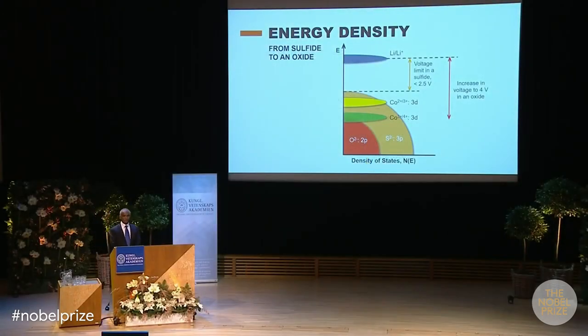There were two major issues with the sulfide cathodes. First, we cannot get more than 2 or 2.5 volt. Second, the sulfide cathodes did not contain lithium ions in them. Therefore, one has to use lithium metal anode that posed safety concerns, fire hazards. In fact, there were attempts to put lithium batteries containing lithium metal as the anode into the market, but then they were abandoned in the 1980s because of fire hazards.